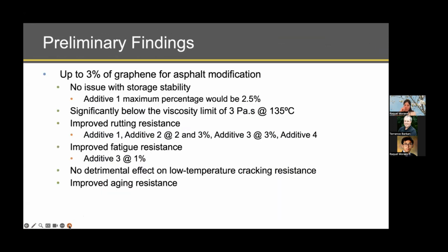So overall, from what was presented today, we saw that for all the additives evaluated in this study, up to 3% of graphene was positive. No issue was observed regarding storage stability, meaning that none of the additives at the dosage up to 3% show tendency for polymer separation, meaning that, for example, if this blend of binders were stored in a tank, we wouldn't have separation between the graphene and the binder.